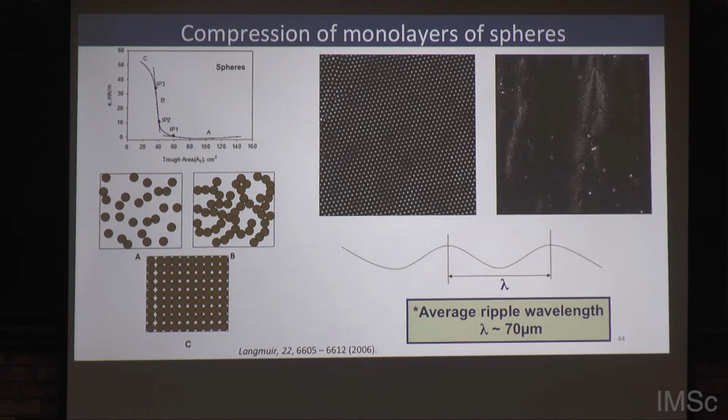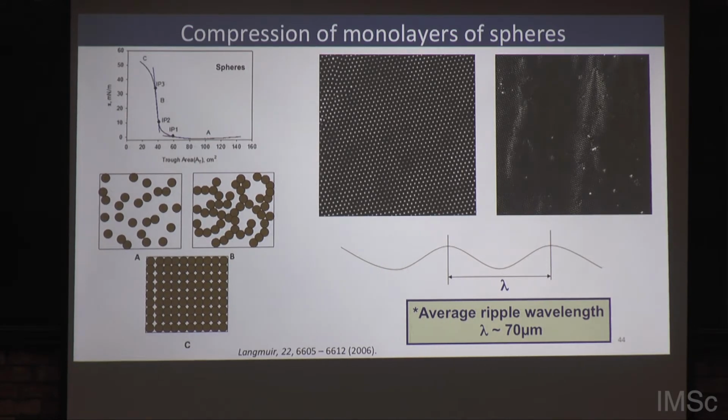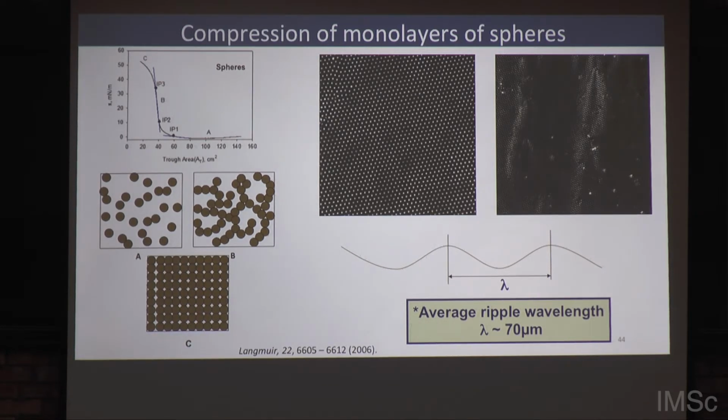In this case, when we release the barrier at, say, junction B, it turns out some of the aggregates remain. That means some kind of interactions also play a role in this problem. So we really cannot think about it as a truly hard sphere system. There are definitely some interactions, which we think are because of interface deformation, which can lead to some capillary attractions.